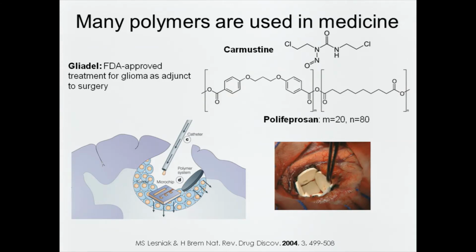And this polymer is very specifically developed for this application. The degradation time is about 3 weeks. So this subunit degrades extremely quickly. This subunit, a polymer composed only of that, degrades very slowly. So they've really tuned the ratio between the 2 polymer types to have optimal properties for the application.